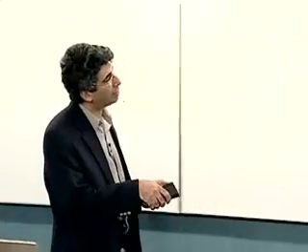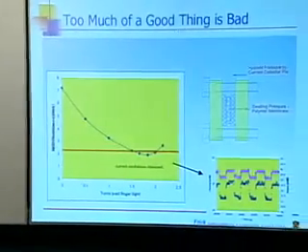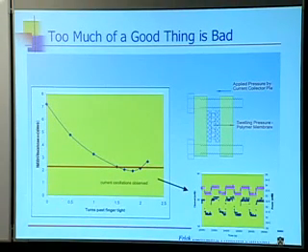So we're looking at the cell resistance right here. We're a little messed up on this axis, but it's cell resistance taken off the linear part of those current voltage curves. And he's doing that as a function of the number of times he turns the bolts on this thing. And at first, you'll notice the resistance goes down. That's always a good sign as you turn the bolts. And then it hits a minimum, and then it starts going back up again. And at the same time, he finds in this region where there's a minimum, that is below the red line here, when he looks at the current response or the voltage response, that it starts to oscillate. That's always a bad sign in electrochemistry.